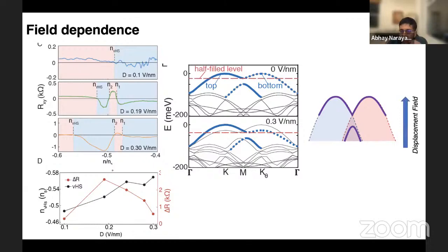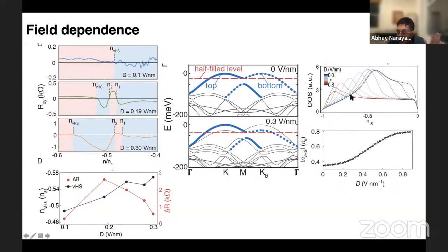Now, you can go even further and ask in theory, what does the band structure look like only within this topmost valence band? If you do that, here's a picture of what DFT tells you for the band structure. If you look at the density of states, at zero electric field, the density of states has a peak, a Van Hove singularity, which is around 0.4 times the filling. So it's on one side of half filling. And as you start to apply this electric field, this peak goes to half filling first. And then as you keep applying more electric field, this peak goes through half filling and goes towards full filling. So there's a range of electric field where this peak in the density of states is close to half filling. And to cut a long story short, this is more or less where we see insulating behavior appear in the sample.